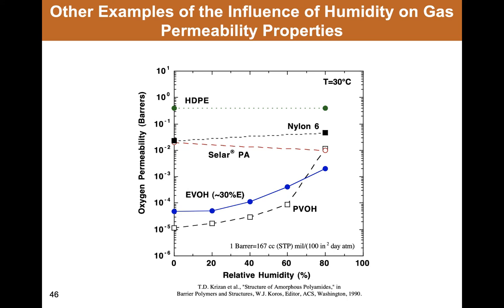And so the point of this is that these second component effects can either be negligible, in the case where the components both sorb into the polymer at very low levels and the oxygen and water are essentially permeating independently of one another. They can be in competition, as in this glassy material, where the presence of humidity actually inhibits oxygen transport. Or the presence of a second component can markedly change the transport of other components, as in the case of the impact of relative humidity on oxygen transport through a highly hygroscopic polymer.